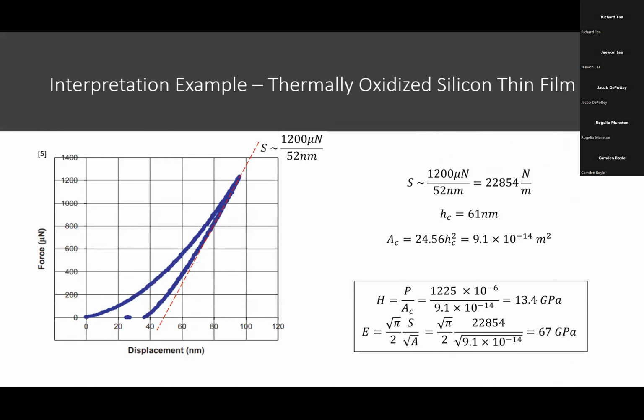Here's an example of how you would interpret results from a nano indenter. This was done on thermally oxidized silicon thin films. You have your force displacement loading curve on the left, and using the slope at the initial point of the unloading curve, labeled S, you could find your unloading stiffness.